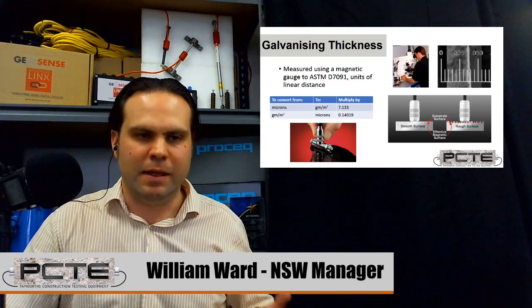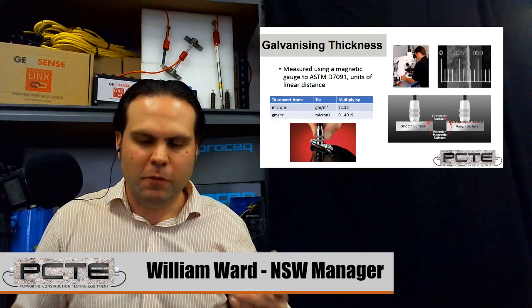The thing to understand about dry film coating thickness machines is they always operate using a magnetic principle. Some of them will use the same principle as a cover meter, which is pulse induction. Others will use a fixed magnetic field. If we use a fixed magnetic field, the only material that field is sensitive to is ferrous metals, so a steel or an iron. And if we instead use a pulse induction, it is now sensitive to non-ferrous metals as well. So if we use a probe that can switch between ferrous and non-ferrous testing, this is how we can evaluate a galvanizing thickness. Because galvanizing is a non-ferrous zinc coating over a ferrous steel.